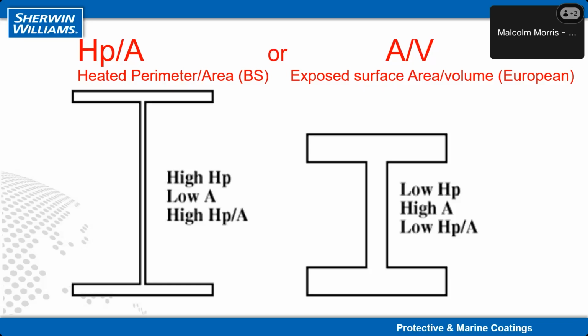With fire protection, it's different because there are two units of measuring effectively the section factor of the steel, which is basically how thin and slender or how thick and chunky the steel is. And so you've got two steel sections there, a thin slender piece on the left, a thicker chunky piece on the right. And if you put those two pieces of steel into the same fire, that thin slender piece is going to heat up a lot quicker because there's much less metal mass there than the thick chunky piece.